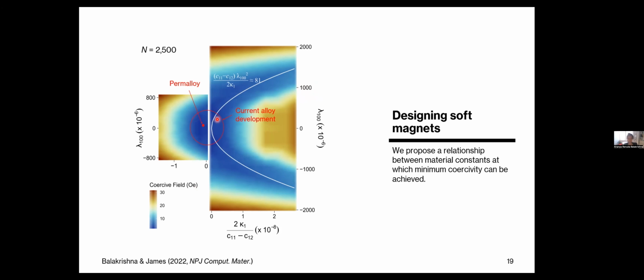So what this essentially suggests is that it produces a quadratic relation between your anisotropy constant and magnetostriction constant, wherein you can expand the alloy search strategy to not just focus on kappa 1 close to 0, but actually tune these constants to lie along this parabola and still develop a soft magnet.